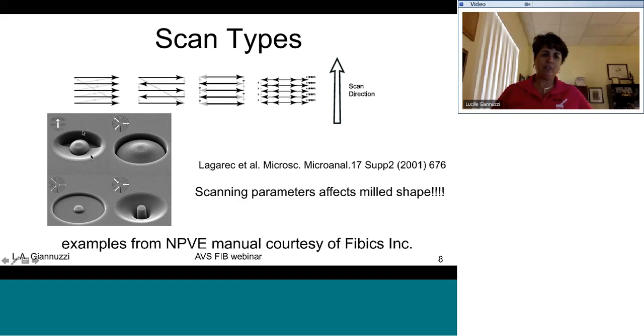So if we have this outer diameter and inner diameter, and if we mill from the bottom part of the pattern to the top, initially we start to mill perpendicular to the sample, and then we've created a little bit of an edge with that first pass. So with each subsequent line of this mill shape, the sputter yield will increase and our pattern will get deeper and deeper and deeper. But as we know, the sputtered material has to go somewhere, and basically it goes behind. And so we'll wind up with a deeper part of the pattern up here compared to where we started, with a not so well-defined center. Okay?